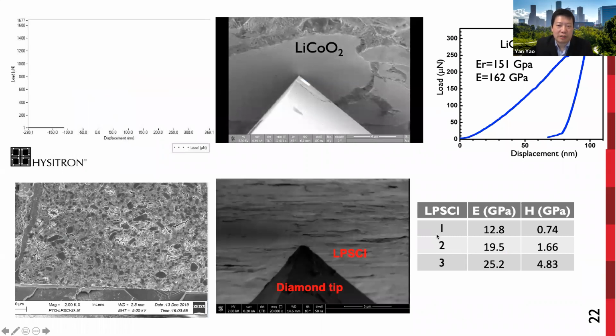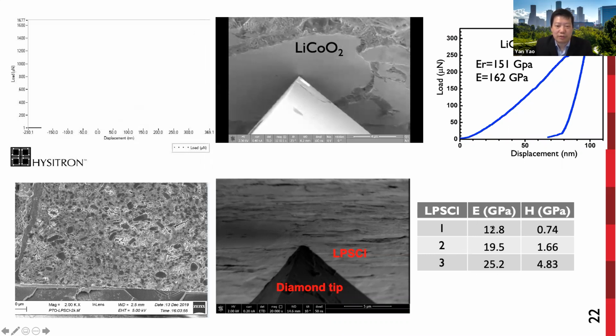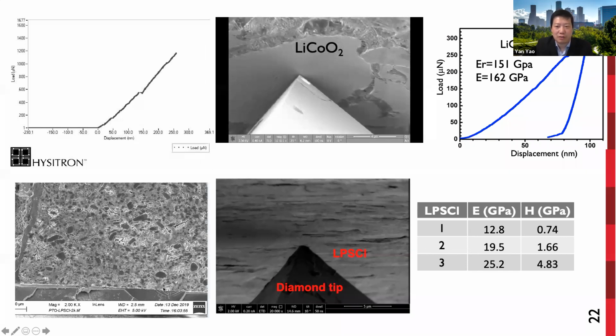So spatially resolved mechanical tests can be performed by locating the diamond tip at different locations. This shows that when the tip is located on a lithium cobalt oxide particle, we can extract the modulus and hardness of the lithium cobalt oxide. If the tip indents the electrolyte area, we will see a measured modulus of the electrolyte one order of magnitude smaller. So in-SEM nanoindentation has high spatial resolution to probe the heterogeneous composite cathode in this case.